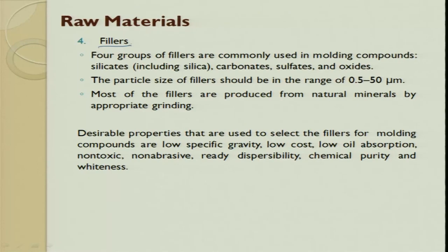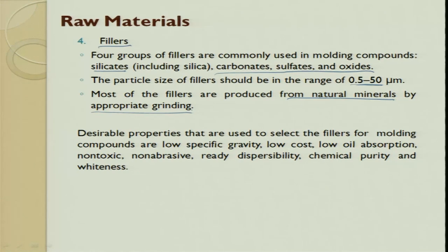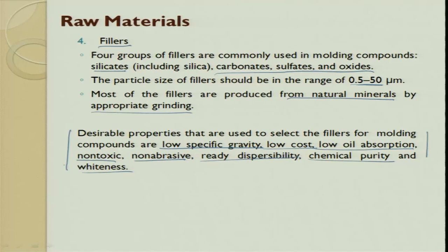There are four groups of fillers commonly used: silicate, carbonate, sulfate, and oxide. Filler particle sizes range from 0.5 to 50 microns. Most fillers are produced from natural minerals by grinding. Desirable properties for filler selection include low specific gravity, low cost, low oil absorption, non-toxic, non-abrasive, ready to disperse, chemical purity, and whiteness. These properties guide the choice of filler for the mold compound.